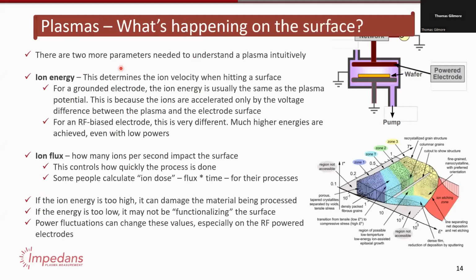Let's go back to the basics for a moment. I'm not sure who's in the audience, but it's always good to start with the basics. So ion energy is essentially the ion velocity when an ion hits the surface. The velocity will depend on the mass, of course. If you're on a grounded electrode, the ion energy is going to be about the same as the plasma potential, because the acceleration is due to the voltage difference between the plasma and the ground. Quite simple. For an RF bias electrode, it's different. Much higher energies are achieved even with low powers. This will be power dependent, frequency dependent, geometry dependent. This is fairly complex.